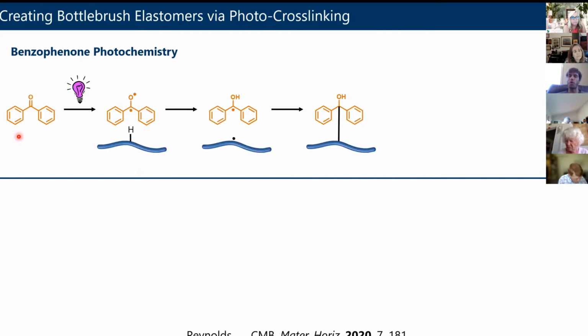that benzophenone is photoreactive. And when you shine UV light on it, which is what damages you when you're sitting out on the beach, damages your skin, it excites the carbonyl group, so it splits one of the bonds and makes a bis radical species. And this bis radical is kind of neat because it can pull off a hydrogen atom, meaning hydrogen radical, off of pretty much anything, especially alkyl groups and types of functionality that are on the polymers we're making. So when it does that, the hydrogen atom will preferentially bond to the oxygen-centered radical, and it'll leave this carbon-centered radical and a radical where you pulled off the hydrogen atom. And these two radicals can recombine and make a new covalent bond.